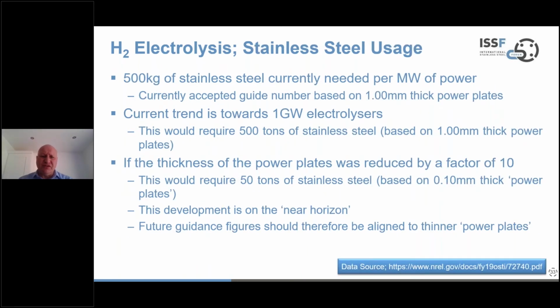And if we think about the stainless usage need, currently accepted guide numbers, which are based on a 1 millimeter thick set of power plates, portray a fact that 500 kilograms of stainless steel is needed per megawatt of power. And that is understood and rather agreed. However, there are two things that we need to recognise. The current trend is towards much bigger electrolyzers, 1 gigawatt plus, and that would require a very significant amount of stainless steel. So if the power plates could be reduced in thickness, and current aims are towards a factor of 10, that would require a 0.1 millimeter thick set of power plates or just 50 tons of stainless steel. And whilst that's still a significant quantity of stainless steel, that development is really now on the near horizon. So I think that's where we need to pitch ourselves for future guidance of stainless usage in electrolysis.